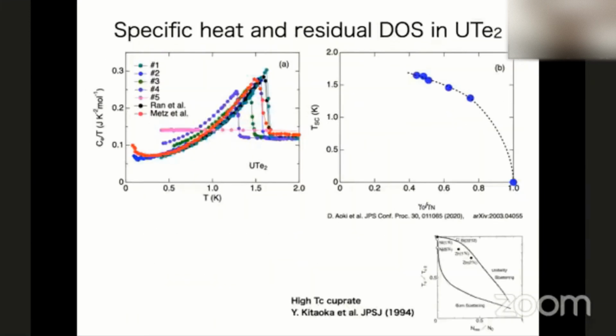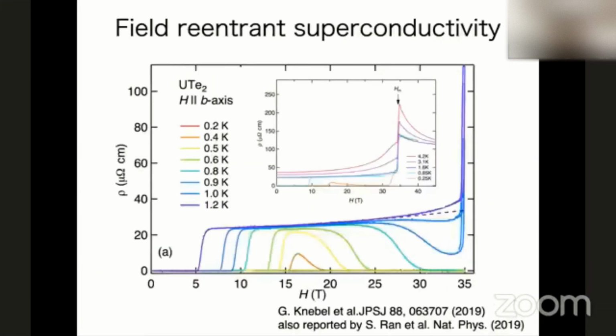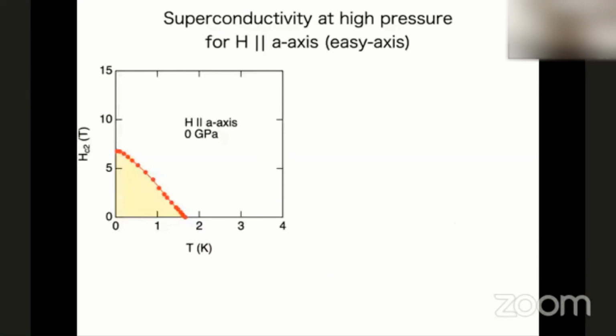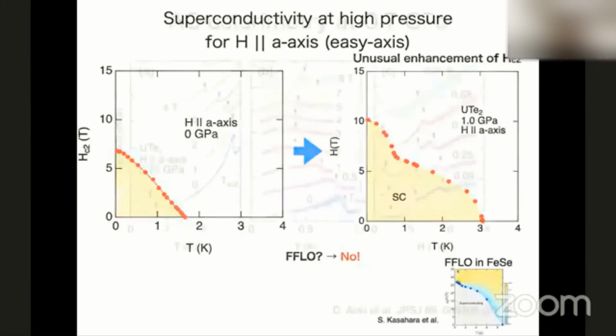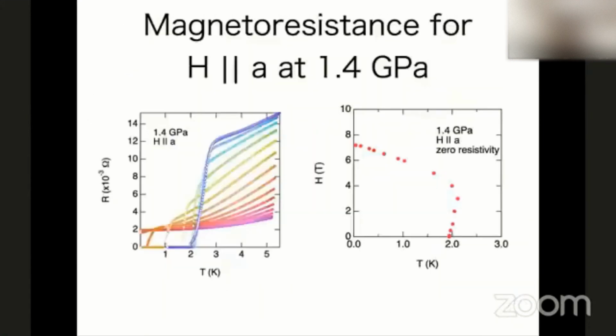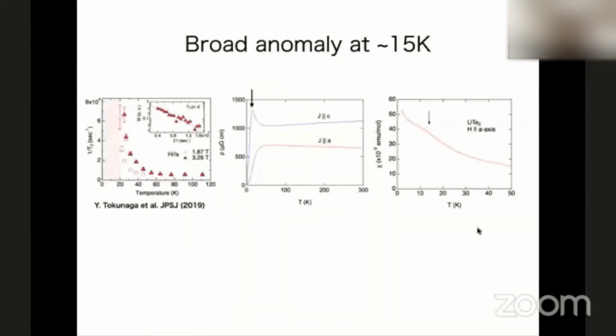results. The resistivity is not very anisotropic, along between the a and c axes. Wait a minute. Yes, so here this is J parallel c and this is J parallel a. You can see it is only twice bigger along the c axis compared to the a axis. If it were a two-dimensional Fermi surface, we could expect an order of magnitude difference between c and a, but it's not so. This is the answer.